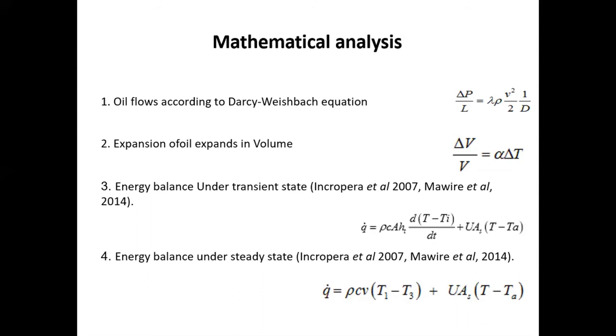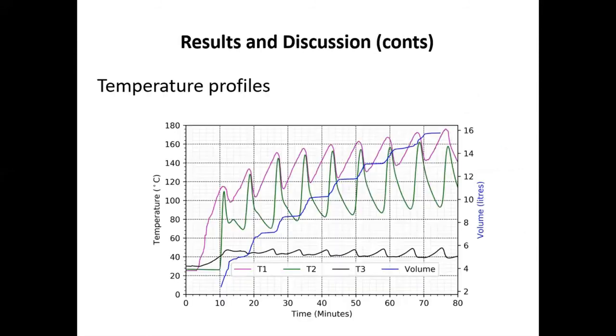So those temperatures were measured initially, and we found that we obtained an oscillatory mode of charging the test system. We can see here that the temperature at the top of the heating chamber was increasing before the slider valve opened. When it opened, cold oil came in, and then it began to cool. On cooling, the oil in the copper coil contracts, and then the slider valve closes, and then we have heating again. So that's why we have this oscillating mode of charging the test system.